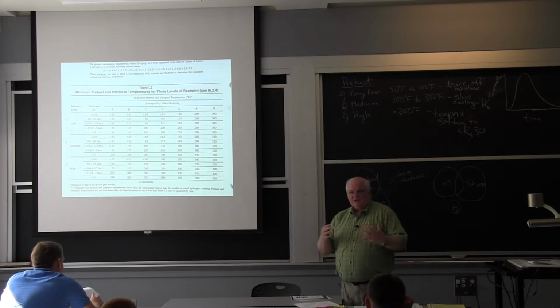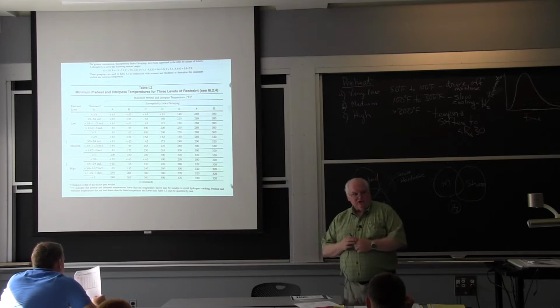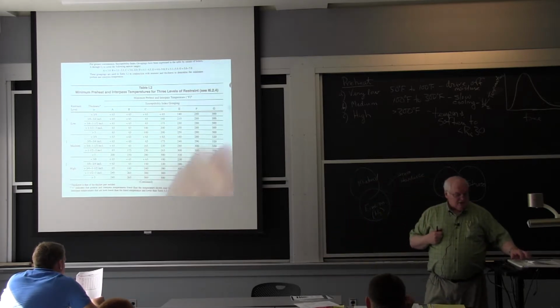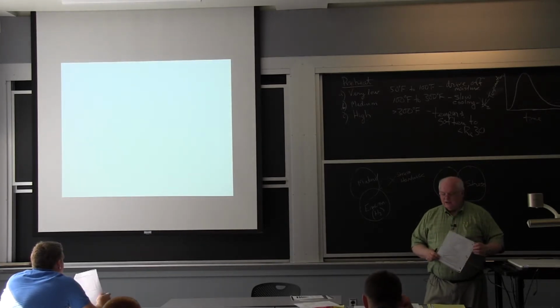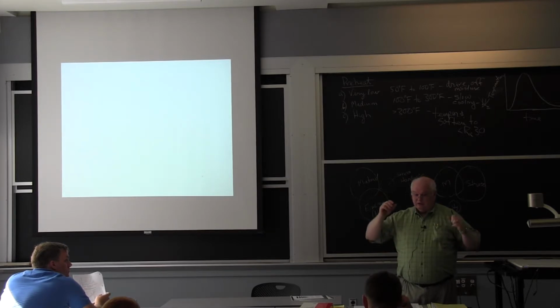Okay? But you can kind of see how HSLA steels can save tens of millions of dollars per ship. And so the surface people use them and the subs don't, because the sub people are conservative, okay? Why are they conservative? They believe that there's not enough history on the toughness of the HSLA steels. They don't have all the work that was done in the 50s and 60s on the explosion bulge test. I showed you the explosion bulge test that Pellini did. They basically take it underwater and make a weld and hit it with an explosive charge and get all those shock waves from the explosion and see if the thing will deform.